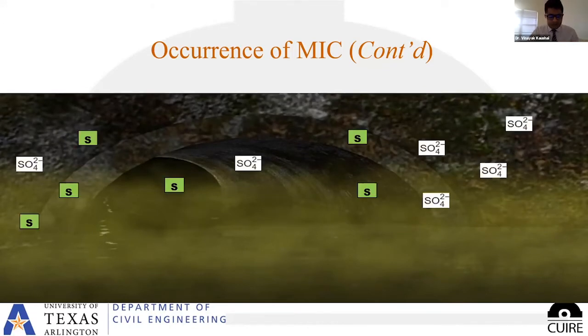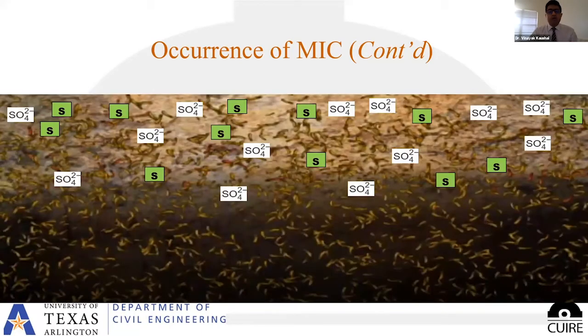So further we see when the hydrogen sulfide gas is released, the sulfur and sulfates are placed on the surface of our structures, which here are the sanitary sewer structures, right? And now we would prefer this process to just stop here, but no, it further introduces yet another bacteria. We'll see how it breaks down the byproducts that were formed previously. As you can see here, these are some of the radicals. So this is where the hydrogen sulfide corrosion actually begins.